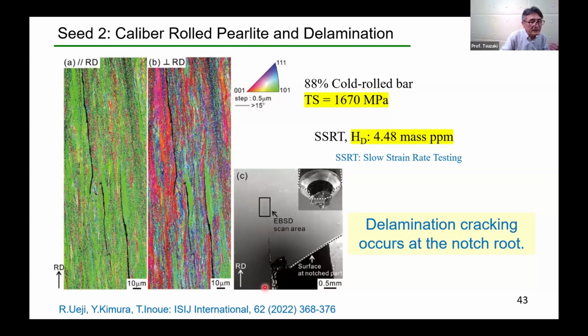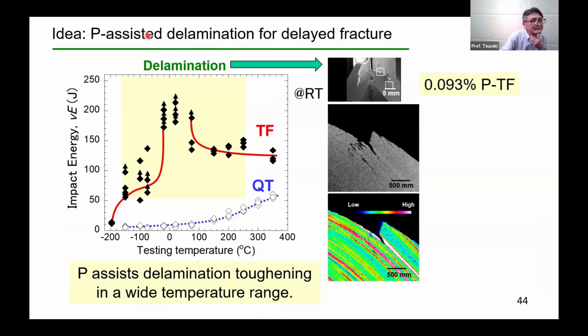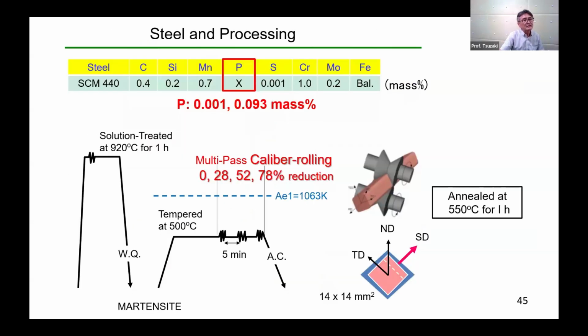This brings me to the idea. I think you all know what my idea is. Yes, my idea is P-assisted delamination for delayed fracture. In this study, we used the same SCM440 with two different P contents. Only two levels of P: 0.001, a high purity one, and 0.093 mass percent, the highest P content.